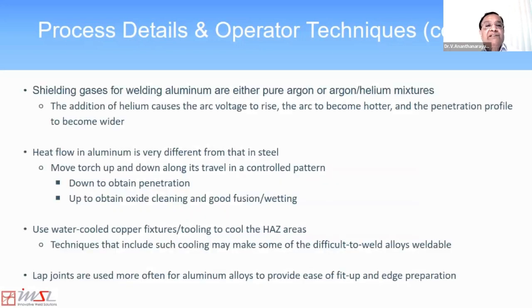Shielding gases for welding aluminum are either pure argon or argon-helium mixtures. The addition of helium causes the arc voltage to rise, the arc to become hotter, and the weld bead to become a little bit wider. And the heat flow in aluminum is very different from that in steel.